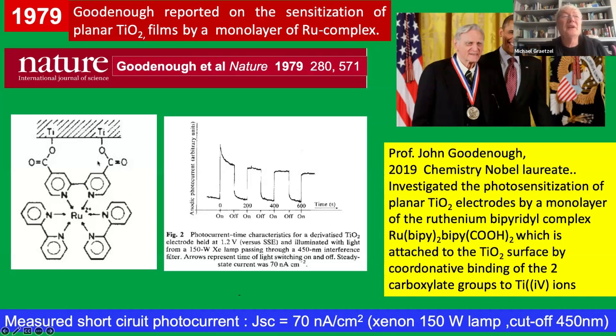He used the ruthenium complex with the attaching groups, these carboxylates that would coordinatively bind to surface titanium ions. And this is a self-limiting process. Once you have saturated the surface sites, there's no more dye adsorption. So it's a way, just by a simple dipping, you can make a self-assembled monolayer on the electrode.